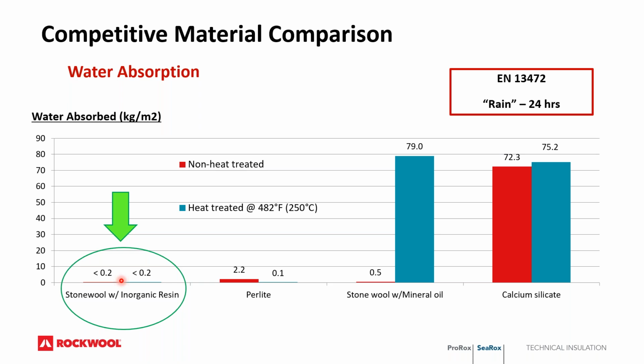But as you will notice, stone wool treated with mineral oil did not perform so well after heat treatment. So this is stone wool with mineral oil, but when it was put into service and heated up, it began to hold the water. Calcium silicate, not so great in water absorption before or after a heat treatment test. We do have a paper that goes deeper into this subject, which I would encourage our viewers to look up, and that's paper number 10929, titled Mineral Wool and Water Repellency.